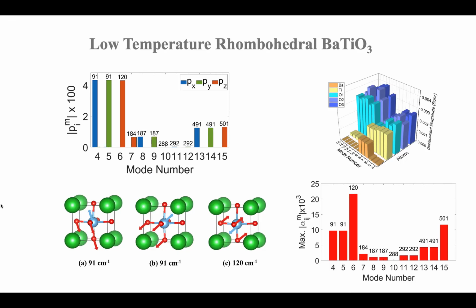So what I'm plotting here is the dipole moment of the mode polarizabilities. This is the Raman response. These are the displacements in each mode at the gamma point, placed by atom. And these are the atomic displacements in the modes which give you a large Raman response. So in essence, in this system, we're kind of lucky. There are 3 modes down here with reasonably high Raman susceptibility. What it means is you move atoms and chi1 changes. And the reason they do it is because you move titanium with respect to oxygen.